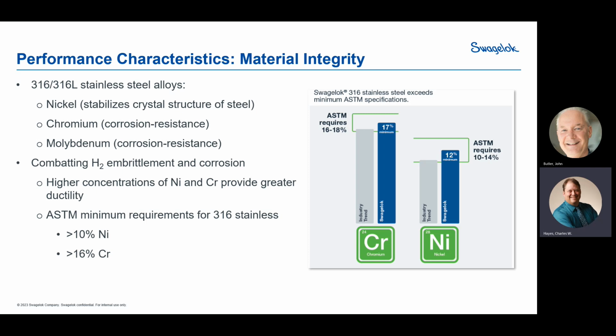But the trick is that there's other characteristics. Nickel is always between 10% and 14%, according to ASTM, and chrome is between 16 and 18% of the material. Why is that important? Well, first of all, nickel is the single most expensive ingredient inside of stainless. So if you're making stainless at 316 and nobody's asking you for anything different, as a mill, you're going to make that at 10.01% nickel if you can. And the reason is you're getting more out for what you're putting in for sale. And in certain cases, that's fine.